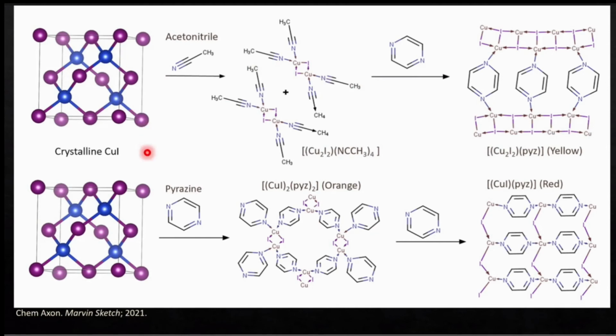The last thing of interest here is that most copper iodide MOFs have been made up to this point in literature using acetonitrile as the solvent. And so in those solution syntheses, we could be only seeing one kind of special case of copper iodide's chemistry because of this mobile dimer phase that does not occur in solid phase chemistry. Does not occur in accelerated aging. And so this is really, really interesting, and it points to that maybe there are other polymorphs of already studied systems that have just not been seen because they used acetonitrile in the synthesis.